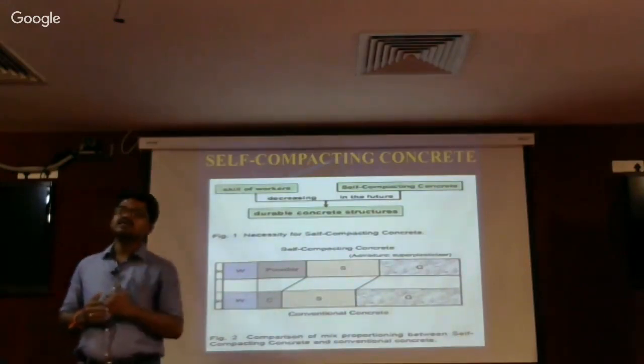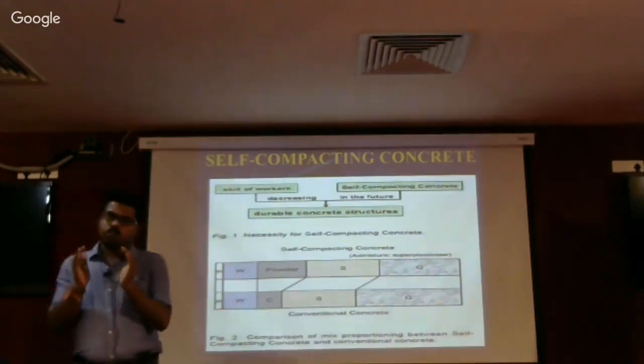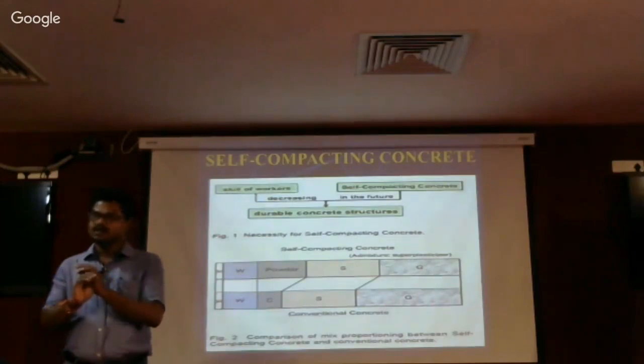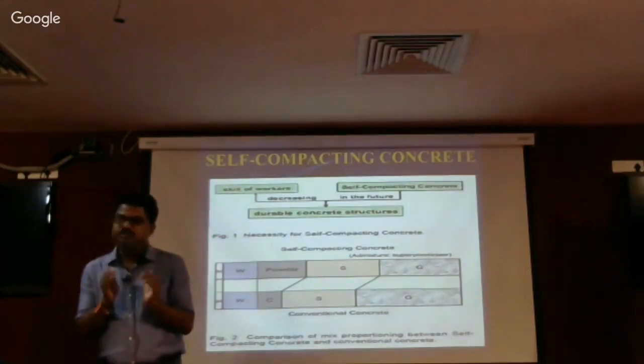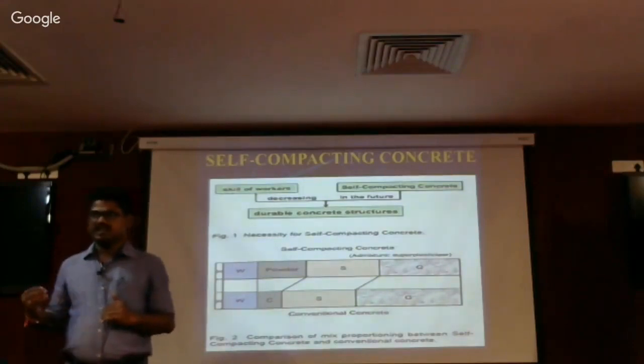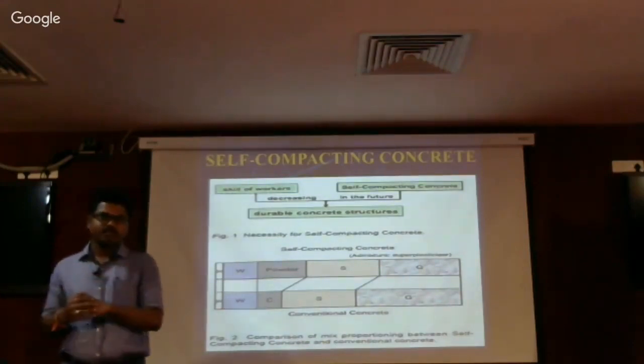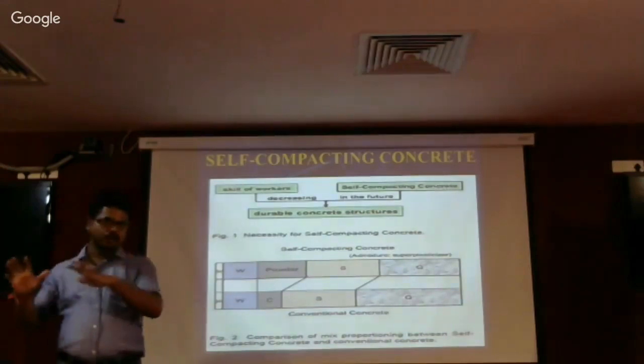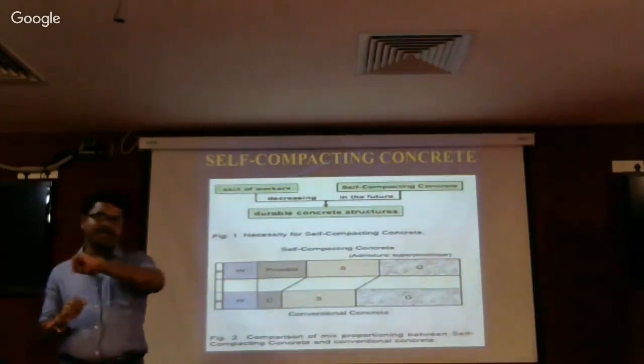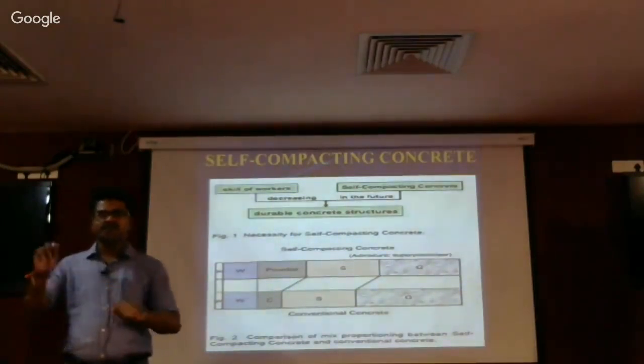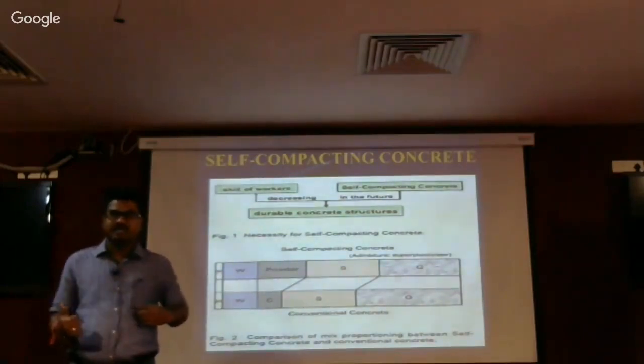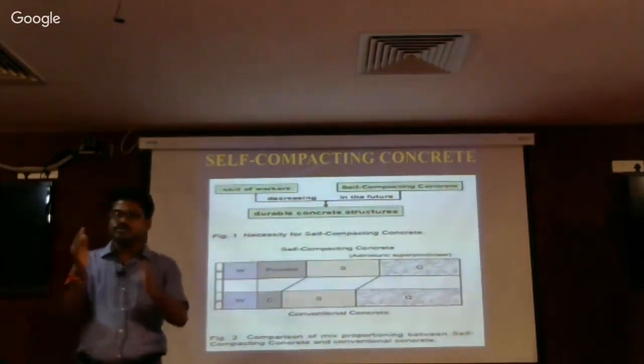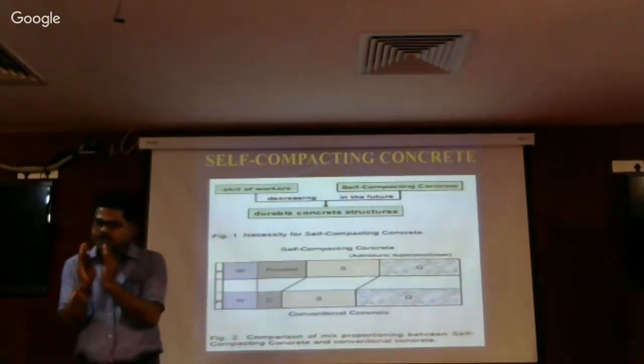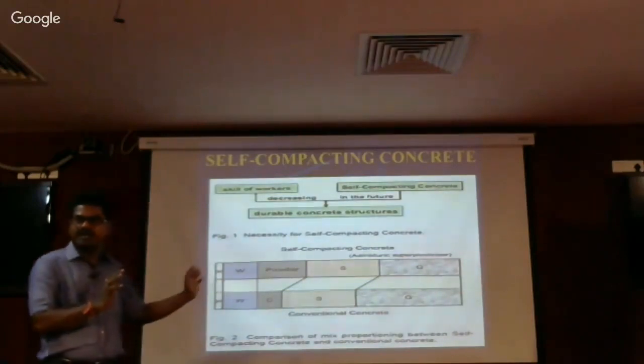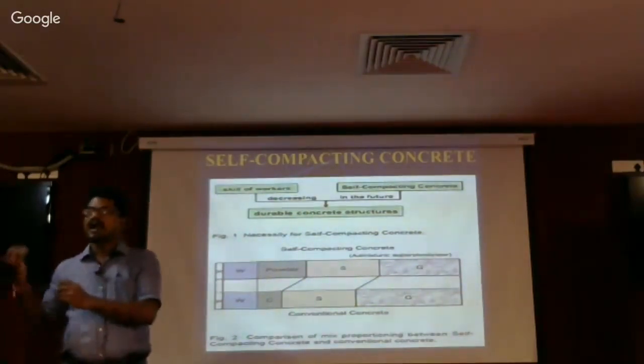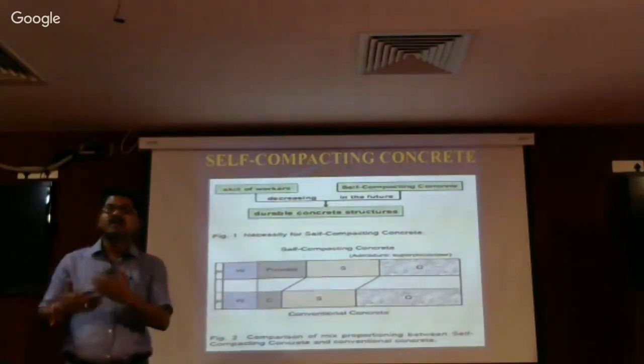So in this method, what he has given as an alternative is that the powder content is required more, but it is not with respect to cement. Whatever the minimum cement required for the hydration process. See, whatever the strength we are getting is because of the hydration process of the cement. When you are curing, it is going under a certain hydration process for 28 days. Regularly, if you are curing the concrete for 28 days, then it is going to achieve its target strength. So to achieve the target strength, minimum cement content is required. Whatever the minimum content of cement is required, that we are going to keep here, and the remaining content we are going to add as fly ash or GGBS, any mineral admixture.